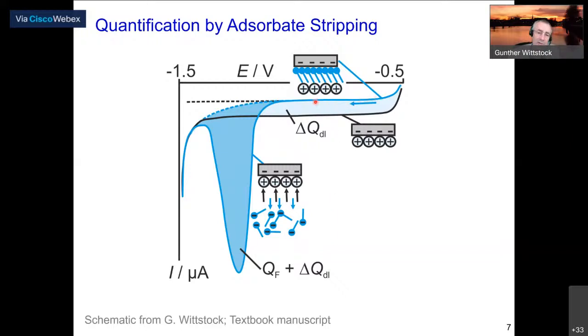If you have an adsorbate on the surface, that adsorbate decreases the double layer capacity of such an electrode. So if we have a bare electrode, then the double layer capacity, so the background curve, would run here. And for a covered electrode, the double layer current, or the background current, is lower. So now if we come to this peak, we reduce or oxidize our adsorbed species. But when they leave the surface, they also automatically increase the capacity of the electrode. So at that point where the electrode is bare, we have again a high capacity.